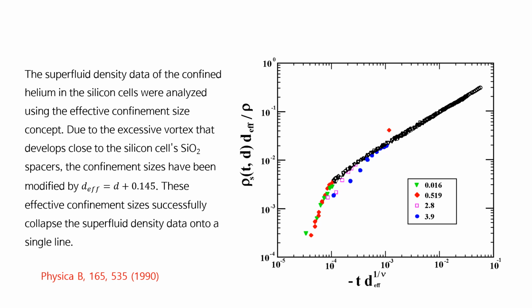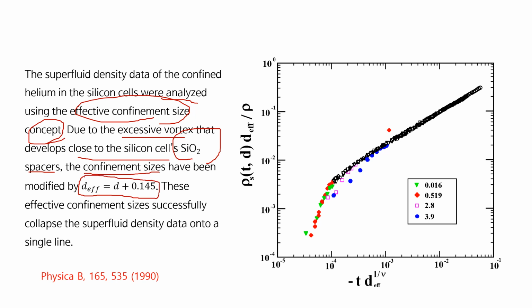However, the superfluid density data of the confined helium in the silicon cell were analyzed using the effective confined size concept. Due to the excessive vortex that develops close to the silicon cell's SiO2 spacers, the confined size has been modified by this function, d plus 0.145. That value is due to the excessive vortex near the SiO2 spacers. So these effective confinement sizes successfully collapse the superfluid density data onto a single line. You can see here.